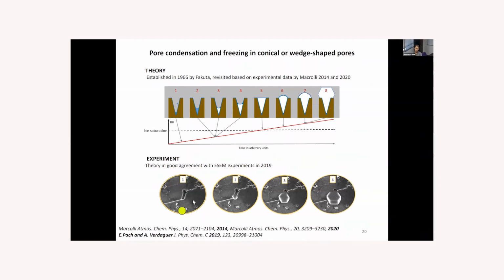And you can see here a pore on the feldspar, which is filled with ice first. And you can see this little ice crystal emerging from the pore, then growing and growing and becoming a big ice crystal on the surface.